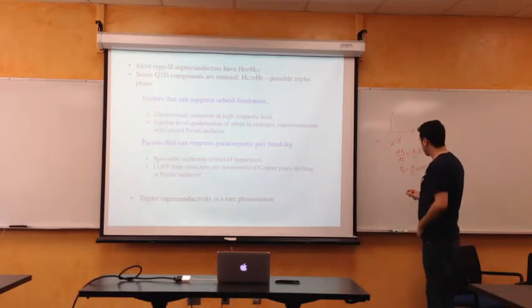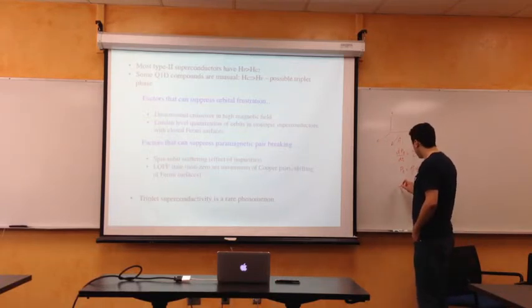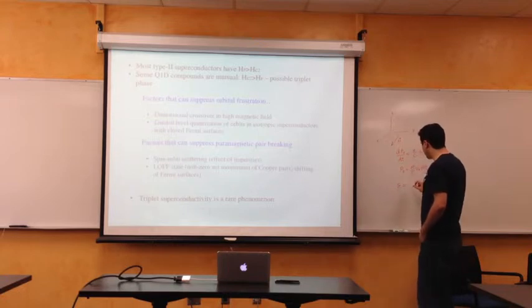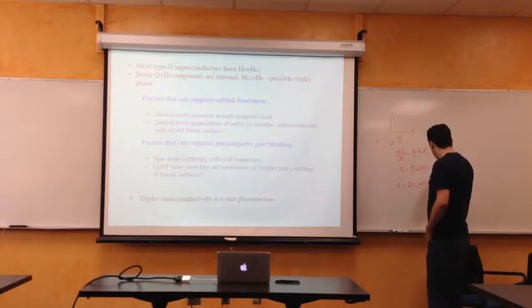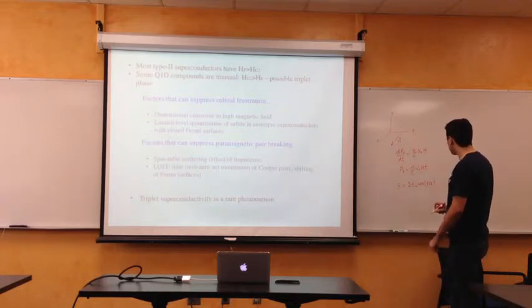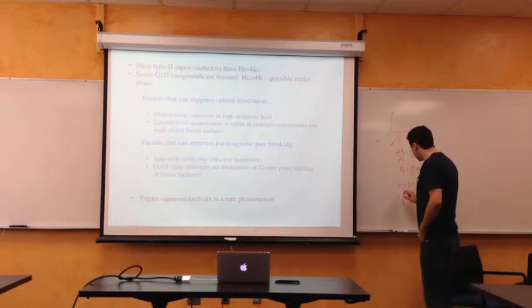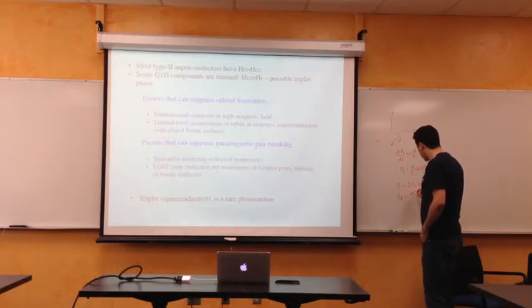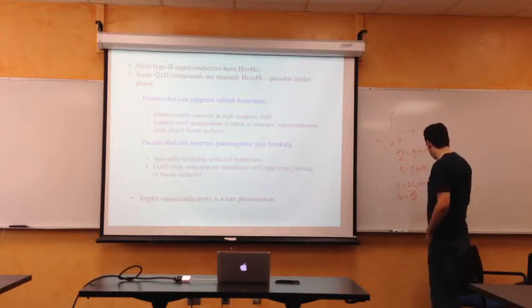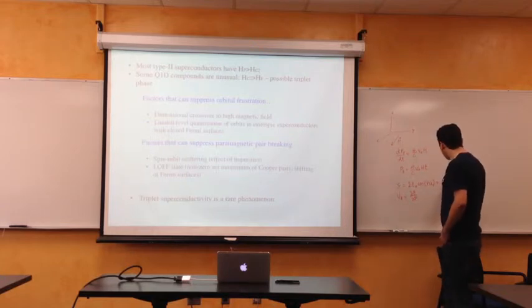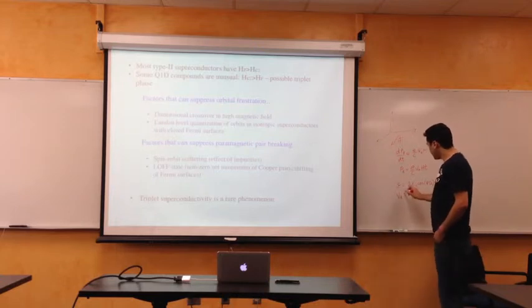Then in the crystal, from the tight binding approximation, we have the energy dispersion relation of the form 2Tx cosine P times some lattice constant A. And then you have Vz from Hamilton's equations, which is just dE/dP. In this case it's actually Tz here, Pz. There are other terms with Tx and Ty, but this is the perpendicular velocity.